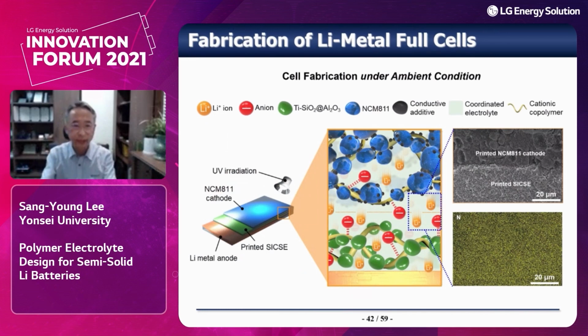And then finally, we have fabricated the full cell. Here, to increase the energy density, we have used the lithium metal anode. On top of the lithium metal anode, we printed our single ion conducting solid-state electrolyte, and we fabricated the single ion conducting electrolyte embedded NCM811 cathode like this. If you look at the SEM image and EDS image, our electrolyte was uniformly embedded inside the NCM811 cathode.